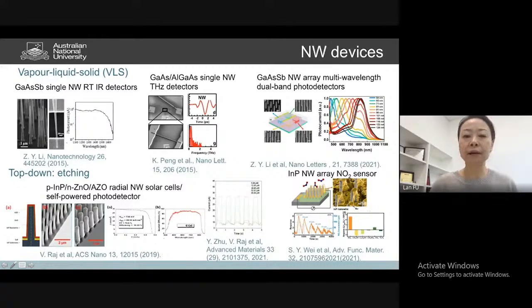We have also done top-down etching of the nanowire by etching the indium phosphide substrate and then contacting that and wrapping that with some zinc oxide material, which we know is a large band gap, but they form some nice type 2 band alignment with indium phosphide. So it's a heterojunction. Thereby we can use that to achieve a radial junction based nanowire solar cell with quite good efficiency and performance. So that's what we have demonstrated.